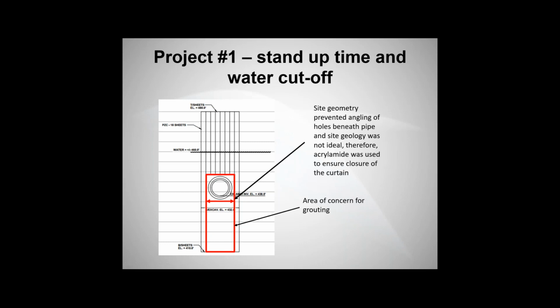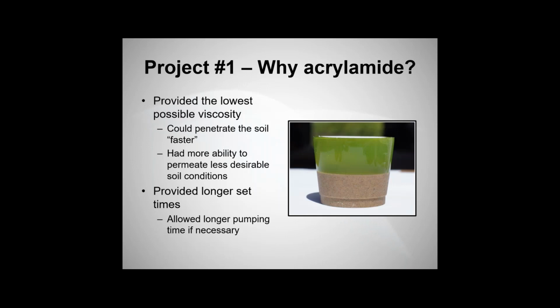This one was a little bit unique in that due to the site geometry, this space was rather wide, and the soil was fairly fine with fairly high fines content, which led us to select an acrylamide simply because we had longer distances to try to push the grout, as well as we thought we may need additional time to push the grout those longer distances. So that's how that was done. This slide goes to that. The acrylamide was the lowest viscosity possible, so it could be pushed the longer distances, and it could go through the smaller particle size and higher fines content, and allowed longer pumping times.